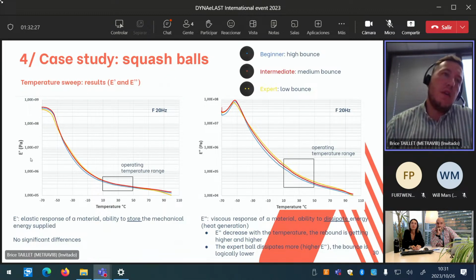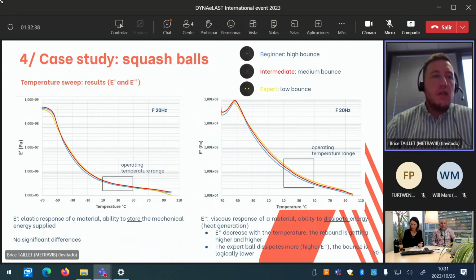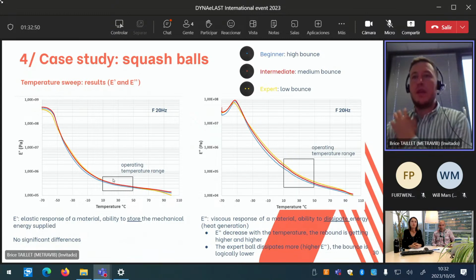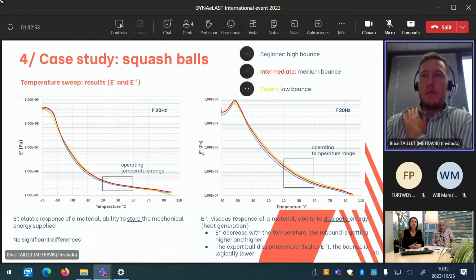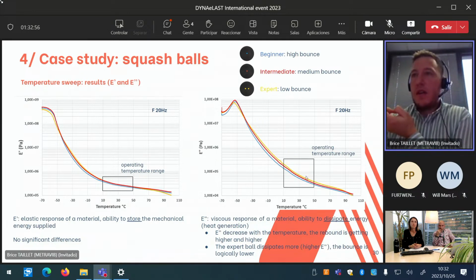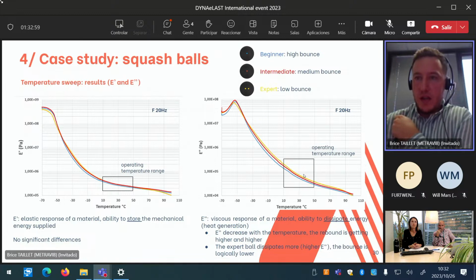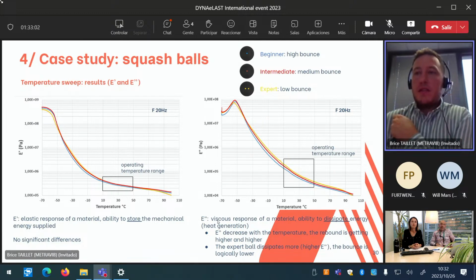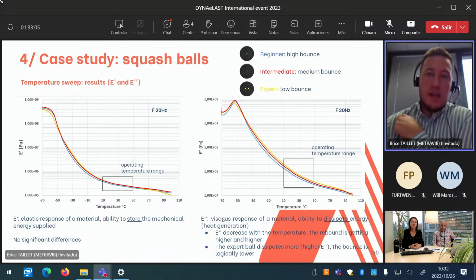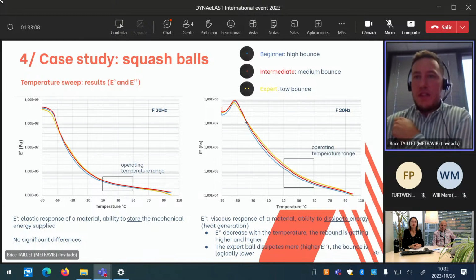As we can see, the evolution of the modulus E' as a function of temperature on the three balls. I just located the operating temperature range during a match. And just as a reminder, E' is the ability to store the mechanical energy supplied. And for this, we observe no significant difference. Okay, the same for E''. E'' is a loss factor. Once again, I located the operating temperature range, and E'' is the ability to dissipate energy by heat generation.